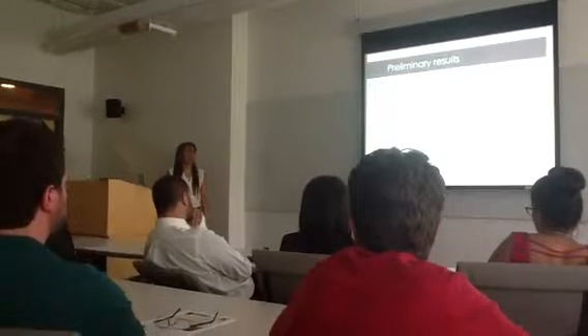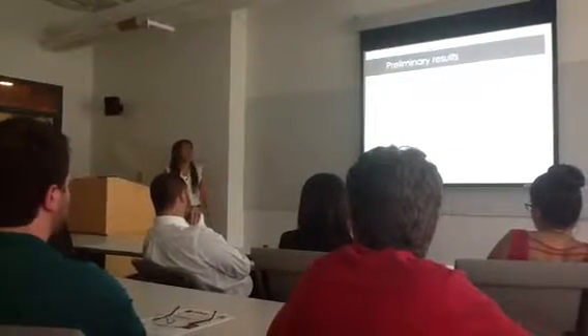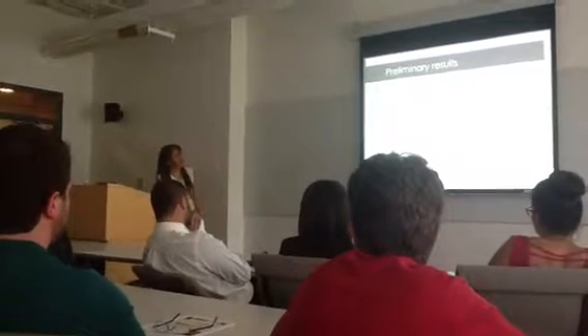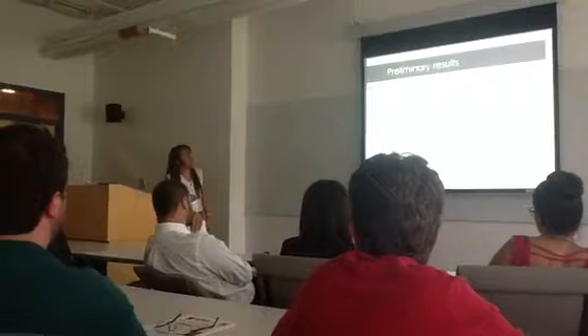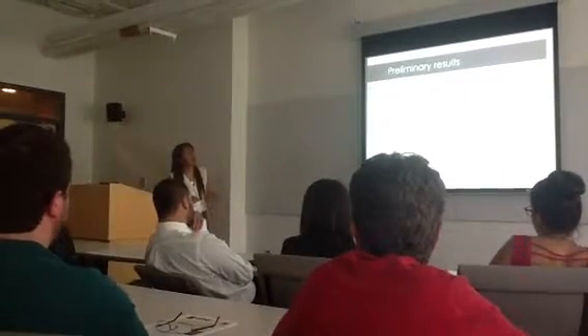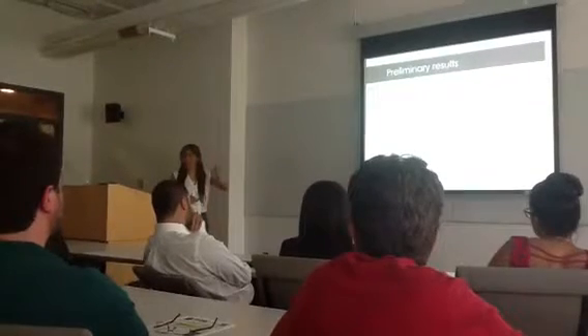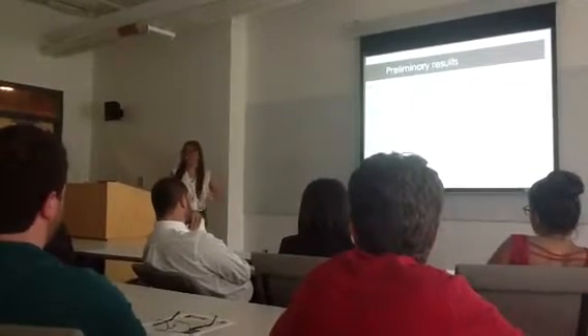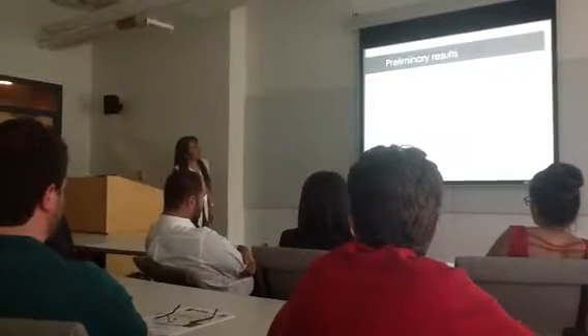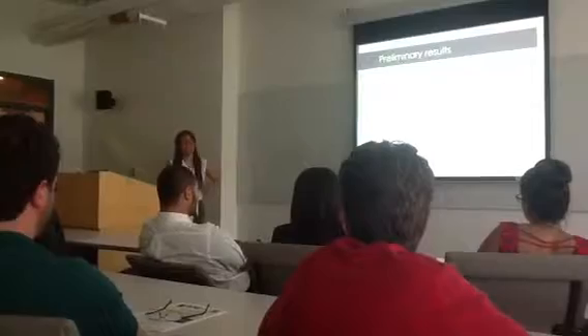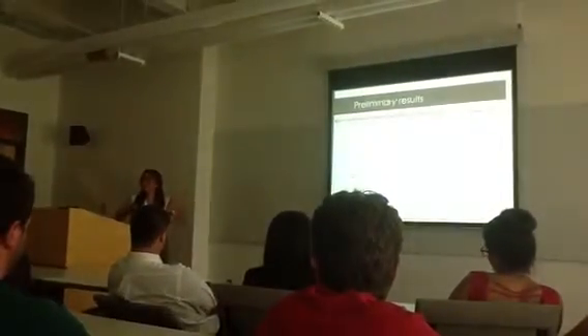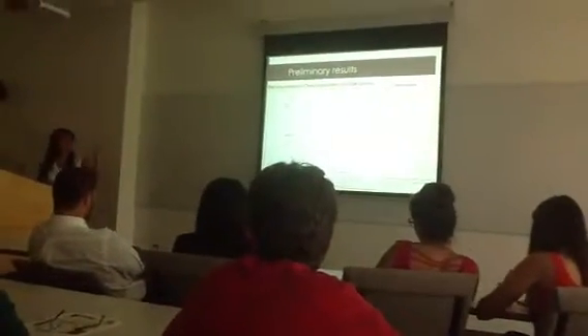This is some of the examples of the results that I obtained during the summer. I'm going to start with the graphs, in which I select 4 of the materials. The one that doesn't have iron, one that has the least amount of iron, one that has the most iron, and one that has something in the middle. First of all, each line or each cycle of the graph is representative of a series of electrochemical experiments that I do. These graphs are made of the overpotential versus the current density. I ran each cycle of each catalyst until it stopped activating, with a maximum of 3 cycles.